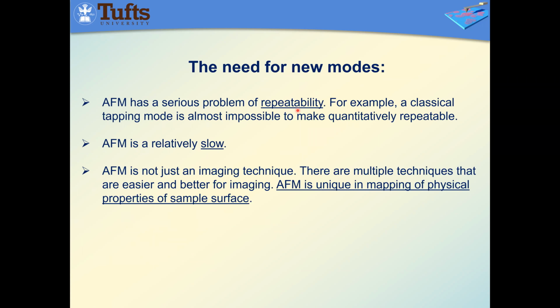So, the need for new modes. AFM has a serious problem of repeatability. That has been almost the bottleneck for broad application of this technique for at least a couple of decades. For example, classical tapping mode is almost impossible to make quantitatively repeatable. There are, if I'm not mistaken, maybe 100 works trying to quantify phase imaging, but it's so sensitive to everything in the world that it hasn't been done as yet. AFM is also relatively slow, and that's a fact. Of course, you may know that there are so-called video rate AFMs. Those are really narrow and mostly for high-resolution imaging of fast processes. I still have to see applications beyond just a few molecular images, which were really impressive, but just literally a few.